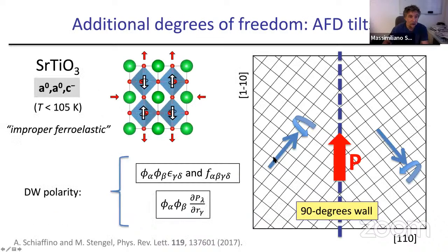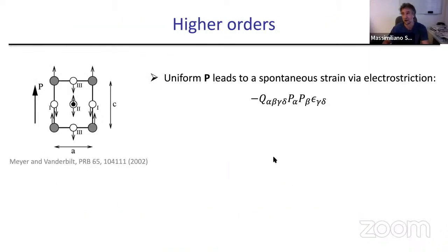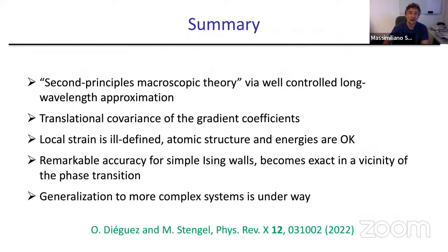This takes too long to explain, but flexoelectricity in a way is a non-analytic elastic contribution to the gradient coefficient. You know about non-analytic electrostatic contributions, but here when we look at dispersion effects, we also get non-analytic elastic effects, which makes sense because elasticity is also long range, like electrostatics.